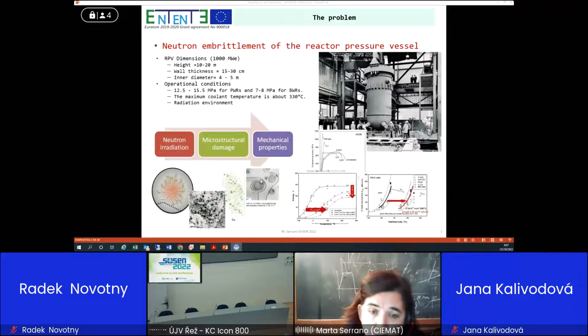When we talk about neutron embrittlement, we need to take into account that it is a multi-scale phenomenon. That is, the neutron irradiation affects the microstructure, creating defects. And this microstructure-induced defect affects the mechanical properties of the material. That is, when we study neutron embrittlement, we need to go from the very basic physics concepts through all the microstructural techniques, most tensile, Charpy tests, and also fracture toughness tests. To go from this atomistic level to the fracture toughness is a challenge. And we need to understand the atomistic effect to try to understand better the mechanical properties effect.